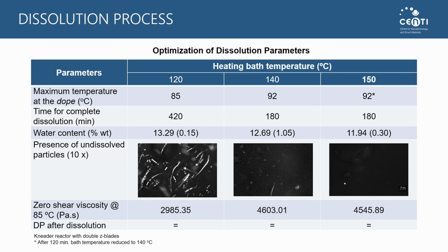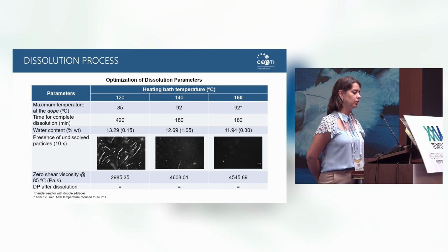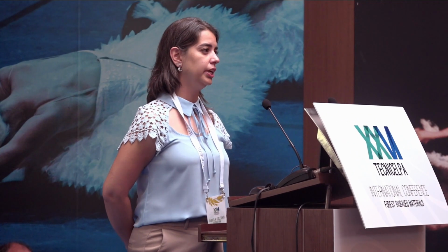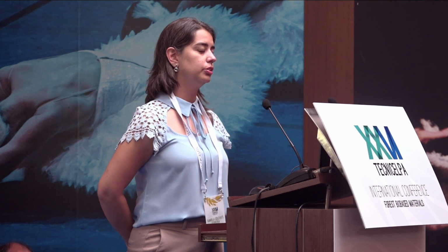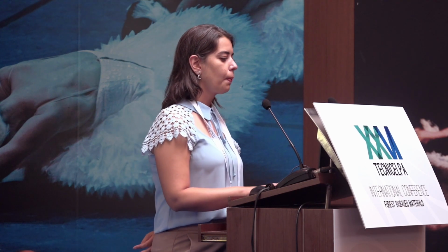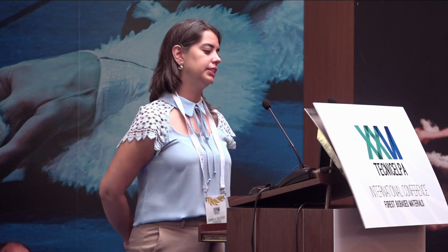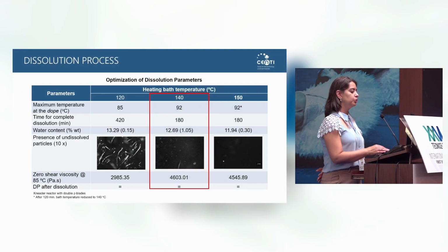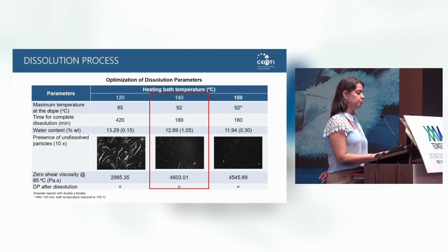We measured the zero shear viscosity of these dopes, and we saw that the lowest temperature also had the lowest zero shear viscosity because we didn't dissolve all the cellulose. We also measured the DP of the precipitated cellulose, and it was similar to the initial one, showing that we do not degrade the cellulose. Based on these results, we chose the temperature of 140 degrees to go to the spinning experiment.